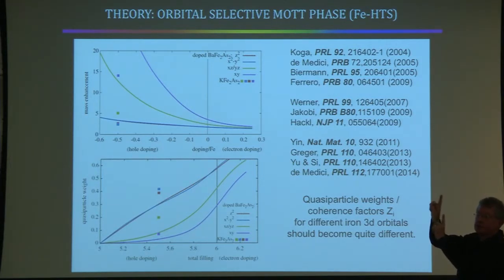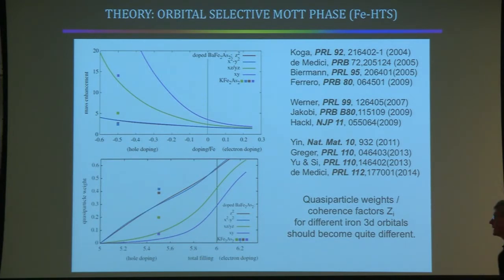Suppose you have 2 orbitals, and they're split from each other, and they could undergo orbital selective Mottness. Now, as you alter the chemical potential, you bring it closer to the upper orbital. That means you push the upper orbital closer to half filling. If there are strong interactions, then the upper orbital can become a Mott insulator, leaving the lower orbital in a metallic state. And when it does so, the quasiparticle weight should change dramatically, and also it should be different for different orbitals. So this is a strange situation. Imagine a Fermi surface.